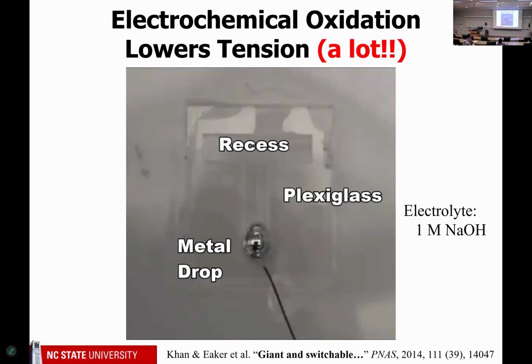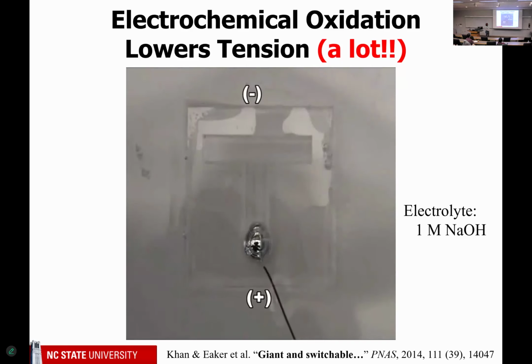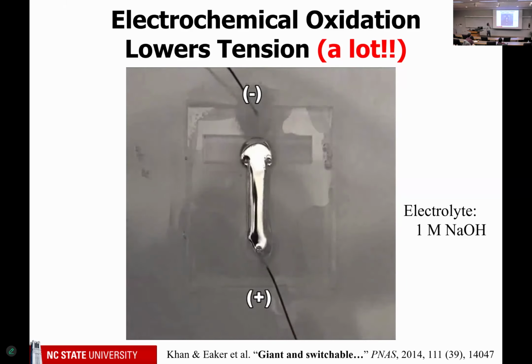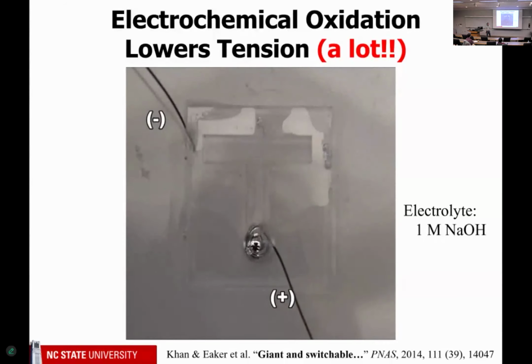Okay, so this was something we discovered kind of on accident, but it turned out to be very interesting. So this is this really large surface tension liquid in sodium hydroxide, so there's no oxide, and we stick an electrode into it and we apply a positive voltage, which means we're going to oxidize the surface. And what you would expect is just a shell of oxide to form on the surface and nothing should happen, right? I've already shown you we can 3D print the metal. Well, when we do this, we apply the voltage, and we apply it relative to a counter electrode, which you can see at the top of the screen. It spreads like a pancake.